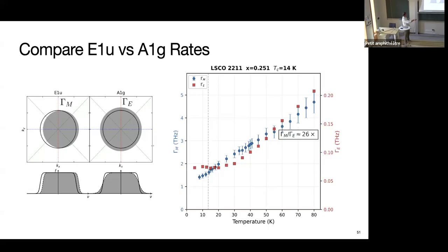But in this whole range where this is linear in T, you don't see the 1/T dependence of the energy relaxation rate. So among other things, one of the things that this data does is rule out electron-phonon coupling as a source of the linear T resistivity of the cuprates, right? I just don't see any way that that is possible with this data at all.